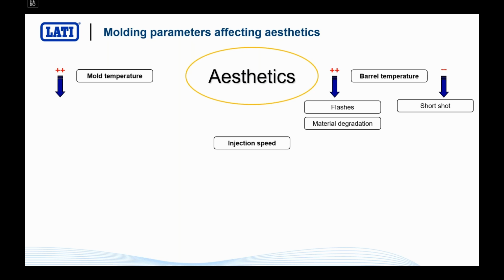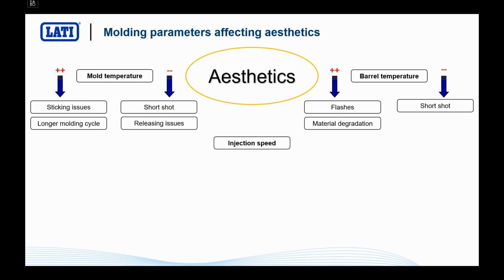What happens if you have a too high mold temperature? Bad issues. You will have the part sticking to the tool. It will be almost impossible to detach it, because the shrinkage will be higher and the part will be completely glued to your tool, and you will have issues. Of course, you will have a longer molding cycle because it will take a lot of time to cool down, and it is a problem. If the mold temperature is low, you have a short shot as well. You can have releasing issues as well, and you can also have other aesthetic issues that we are going to find out during this webinar.